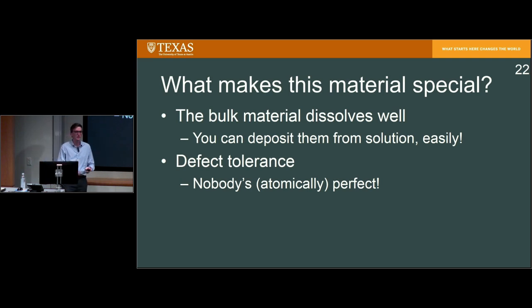In perovskite, not only do you have a much thinner film where these electrons don't have to travel as long of a distance, but when an electron encounters one of these atomic imperfections, either the atomic imperfection is not energetic enough or too energetic, to personify it a little bit, to want to take the electron, or the neighboring atoms next to the imperfection screen the electron, trying to get the electron to move away from this imperfection. So this is what we call defect tolerance, and it allows us to make really, to be honest, really bad films and still make really good devices out of these really horrible films.